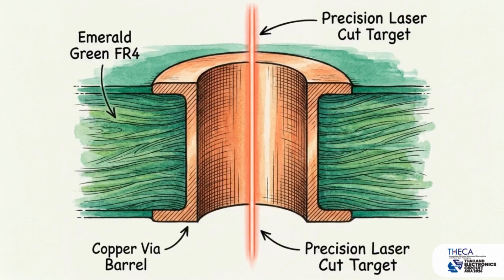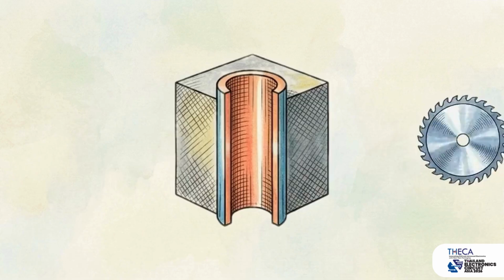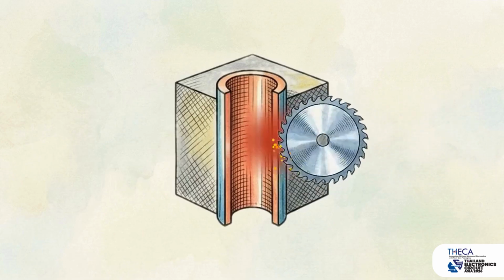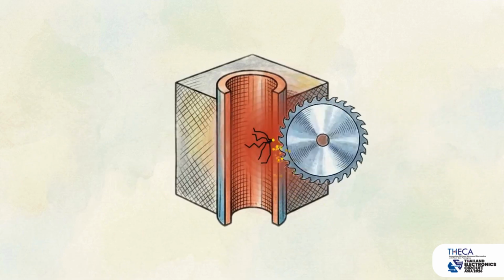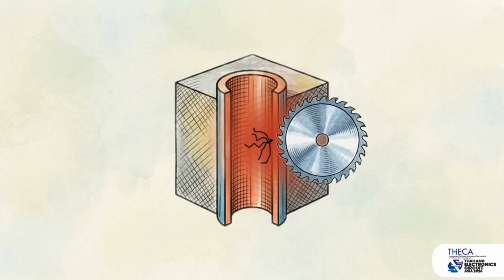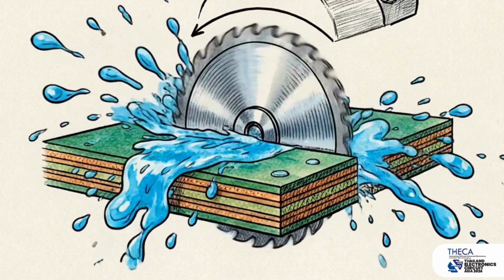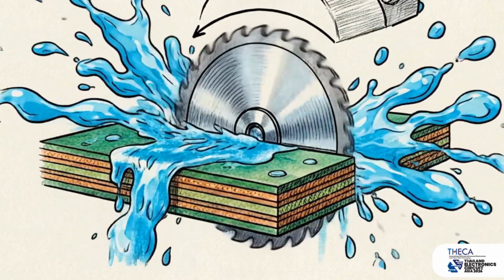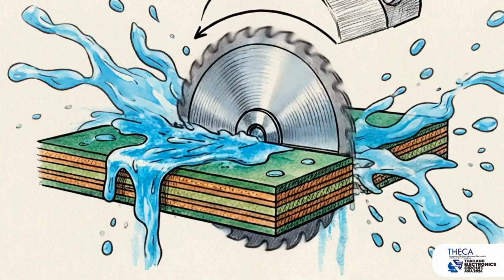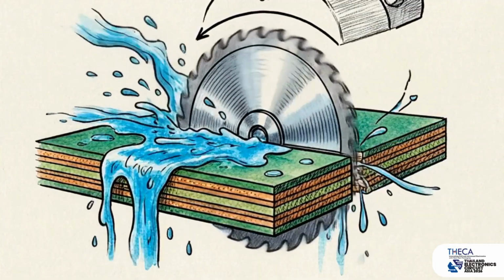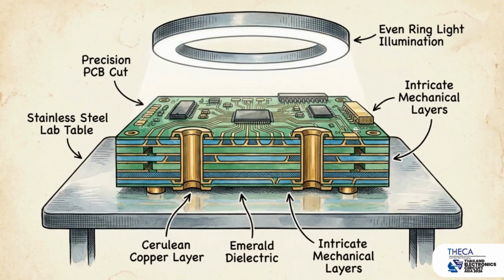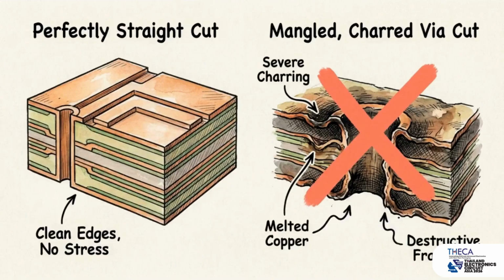The first and most sensitive step is precision cutting to isolate the exact failing via. Analysts cannot use standard rotary tools. They generate friction heat, which would push the FR4 past its glass transition temperature and create new, false cracks. Instead, they use a specialized diamond saw, heavily flooded with a continuous liquid coolant to maintain absolute ambient temperature during the cut. Forensic engineering relies entirely on preserving the truth. Using the wrong tool accidentally manufactures defects, permanently destroying the actual root cause evidence.